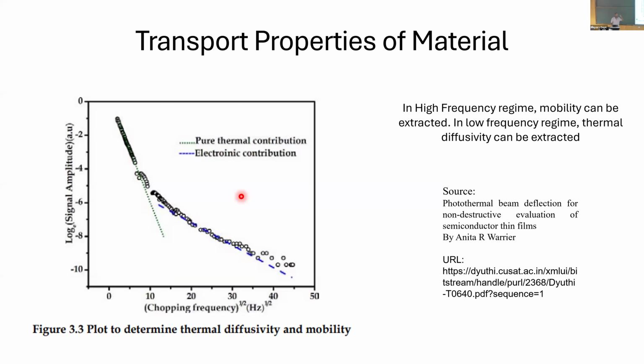This is probably the easiest way to measure the thermal diffusion coefficient. Beyond that, if you stay on one length and change the frequency, you're changing the time associated with the carrier excitation at the same time. In the initial time scale, the process is more thermal diffusion dominated, and in the later, faster time scale, the process is more recombination and carrier transport diffusion dominated. So that's where these two come into picture.